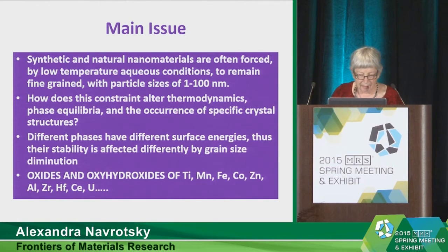So, what about the major issues then? In many cases, be it sol-gel synthesis, hydrothermal synthesis in the natural environment, air particulates, etc., one makes particles, or nature makes particles, or technology makes particles, and those are typically initially made as small particles. And those small particles often persist simply because coarsening requires higher temperature, and in fact requires very often stripping off the hydration layers, the hydration shells on particles, to enable them to come together.